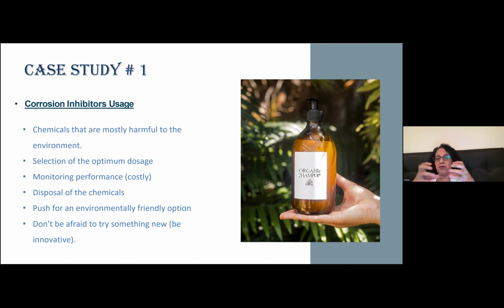So take samples from the corrosion inhibitor, do electrochemical testing using a material, the same material as the pipeline, and measure the corrosion rate. And then 3 months or 4 months later, 6 months later, depending on how critical your asset is, you do another test and you check your corrosion rate. And if you see that it is increasing, then your corrosion inhibitor is not working and you have to act.